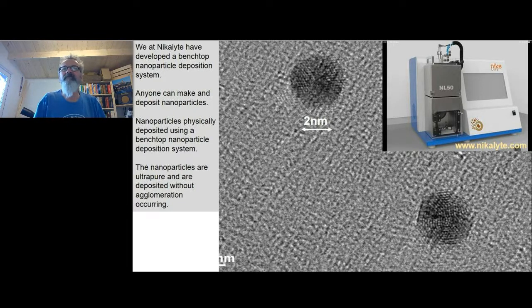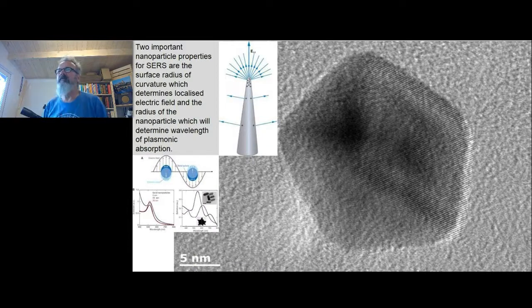nanoparticles. So I've got an example here of nanoparticles, and if you look within the nanoparticle, you can see some small dots which are representative of the atoms within those nanoparticles. So we have to get really good control of the nanoparticles to make our photonic sensor to amplify our Raman signal. I've got an example here of what we call a large nanoparticle, which is still pretty small. But again, if you look there, you can see lines within the nanoparticle, which are lines of atoms rowing up to make this a crystalline nanoparticle of about 15-20 nanometers diameter. But it's these corners, it's these radiuses that give us the electromagnetic effect that amplifies the signal.